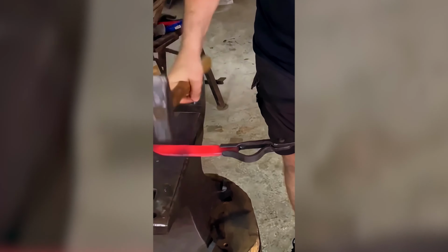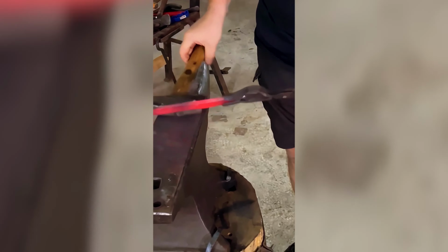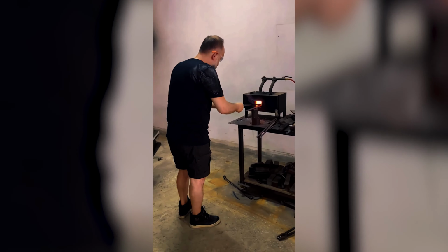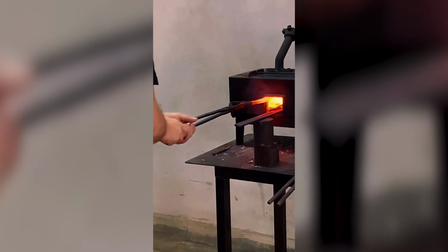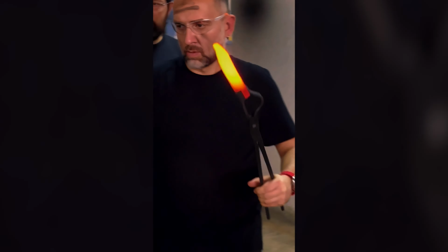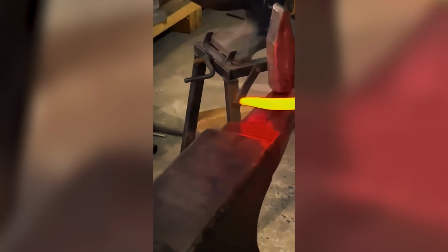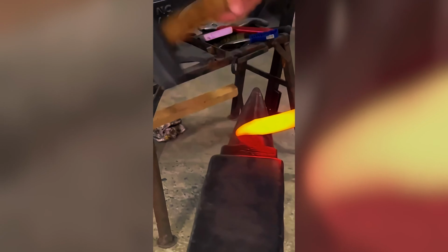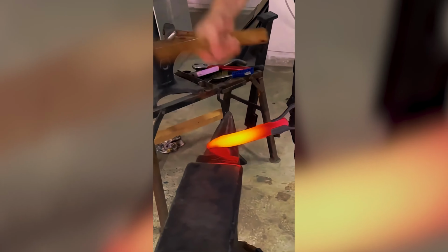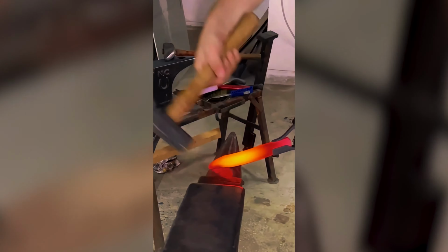While forming the edge line, the blows do not come from a single direction. The hammer is deliberately shifted. The steel is rotated after each strike. This allows the fibers to distribute evenly along the edge. If one-sided forging is applied, microcracks form along the edge line.